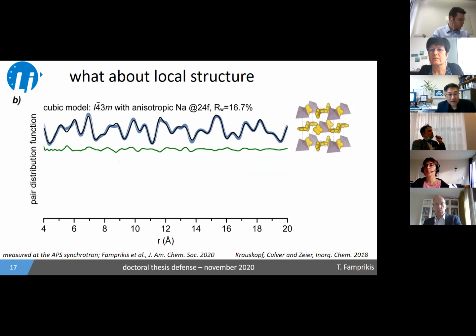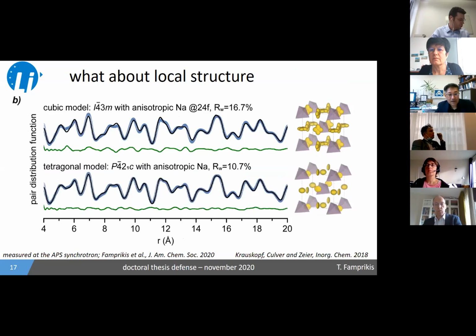But on the other hand, if we actually try and fit the PDF with a tetragonal model, we get a much better fit, or a significantly better fit at any point, indicating that actually locally, even though the Bragg diffraction tells you it's cubic, locally, the structure can be better described by the tetragonal model. And I should highlight that this whole train of thought was developed before from the group of Gießen, Krauskopf et al. And I'm simply validating that result here through my data.